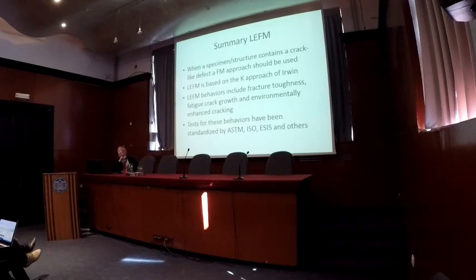So here's some more summary. When a specimen or a structure contains a crack, you should always use the fracture mechanics approach. If you don't use the fracture mechanics approach, you would be missing the effect of the defect. And the linear elastic fracture mechanics is based on the K approach of Irwin. Behaviors include fracture toughness, fatigue crack growth, environmentally enhanced cracking, and